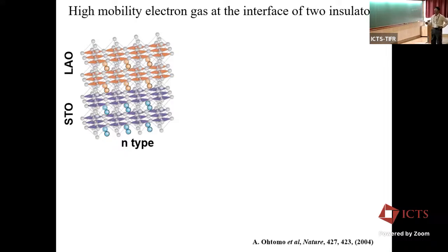If we think about strontium titanate and lanthanum aluminate, you can see that in strontium titanate, titanium is in the oxidation state of 4+. So if you think purely in terms of these charged states to be real, you'll say, okay, titanium is 4+ and oxygen is 2-. This layer has one titanium at the center and 4 oxygens around it, but each of those 4 oxygens is shared by 2. So essentially, I have titanium 4+ and 2 oxygens around it, and that's 2 times 2-. So 4+ and 4-, they cancel, so it's a charge neutral layer. TiO2 is a charge neutral layer.